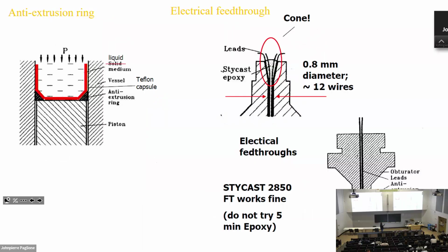Another thing is the so-called anti-extrusion ring. We have this Teflon capsule. If you squeeze too much, the Teflon is very soft. You have a risk of squeezing it into the space between the piston and the cylinder. So people invented this anti-extrusion ring. Basically, it's a metal ring, so that it will not go into this space. Another important detail is this feed-through. Most of the time, the piston cylinder fails because of this feed-through. So you have your sample here, and you have to have some electrodes coming out. How do you make sure there's no leak? So we use some Stycast, and this cone shape is very important. Most of the time it fails because of this.